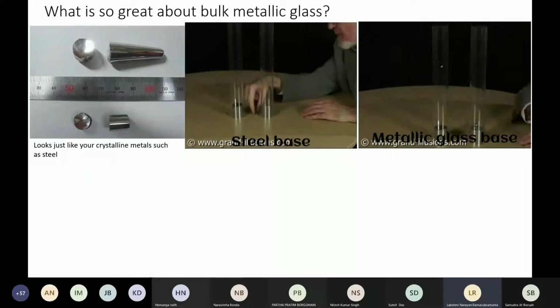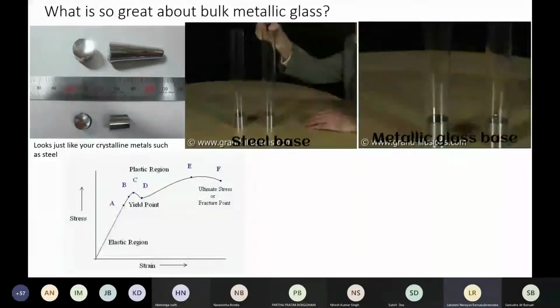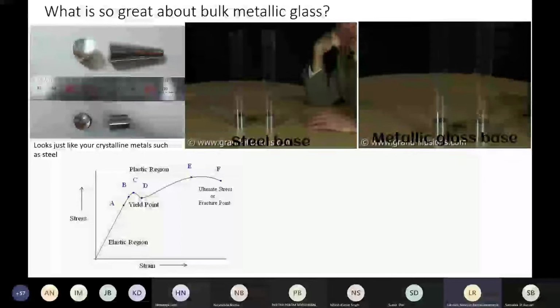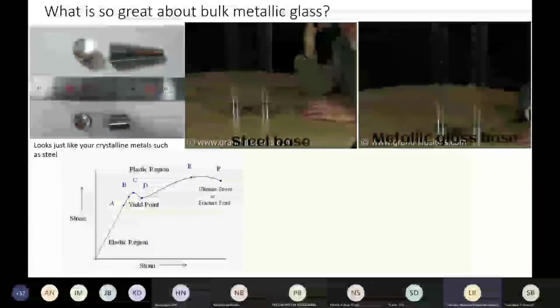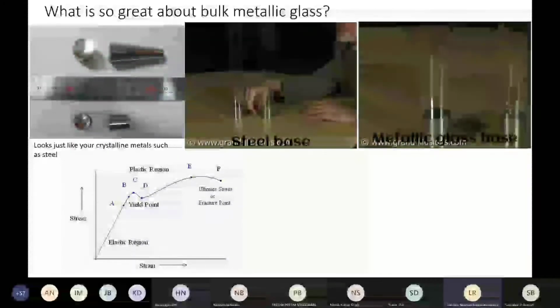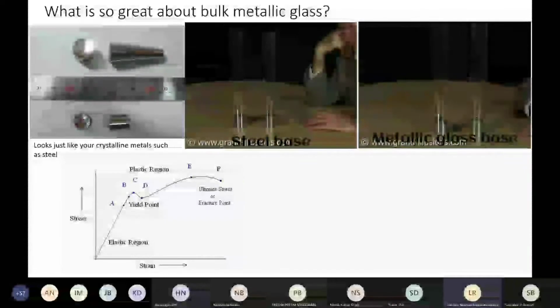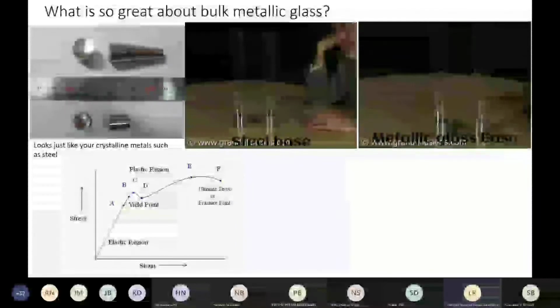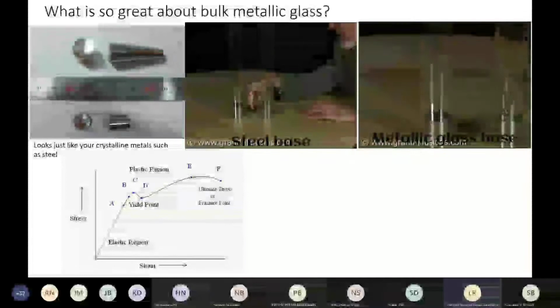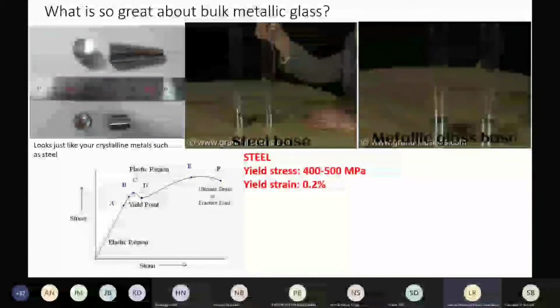So what it implies is that if you look at a stress strain curve, you have an elastic region, a yield point, and an ultimate fracture point. If you look at the elastic region, the steel will have a lesser elastic region than that of a metallic glass. As in, steel will yield at a lower stress than a metallic glass. And that is what we see.